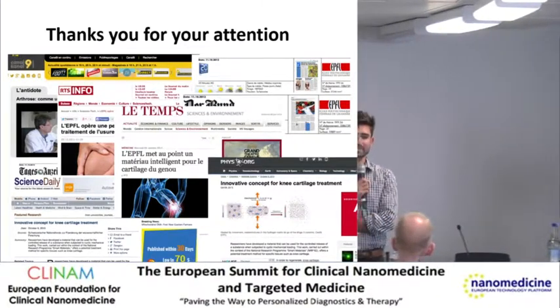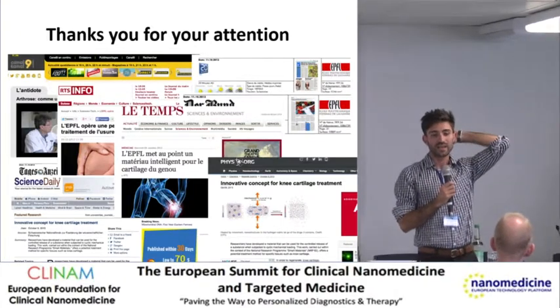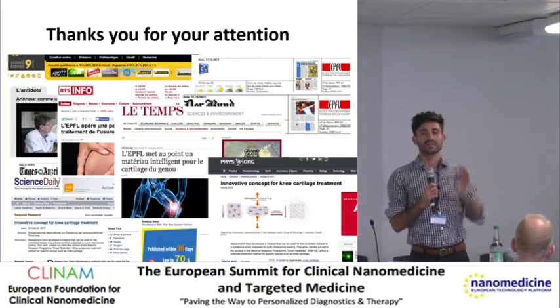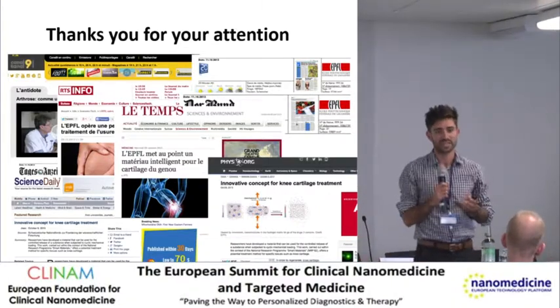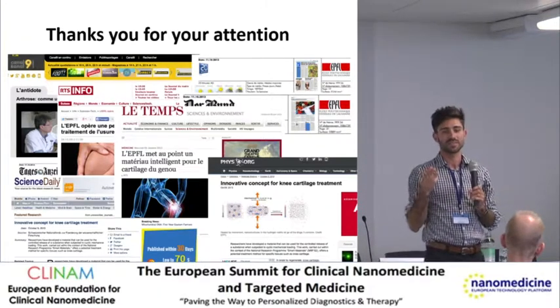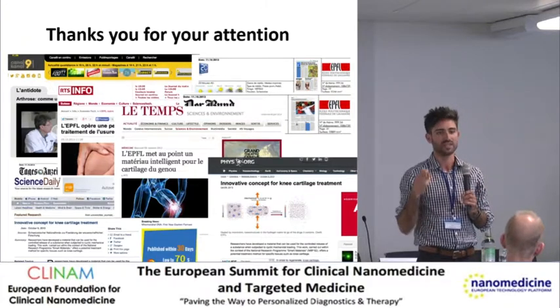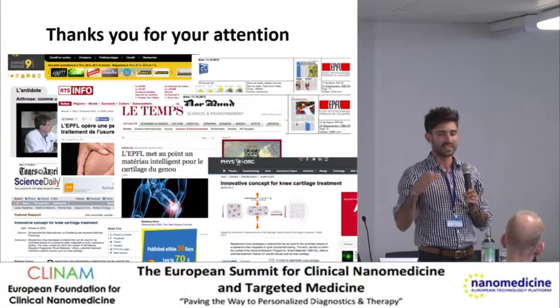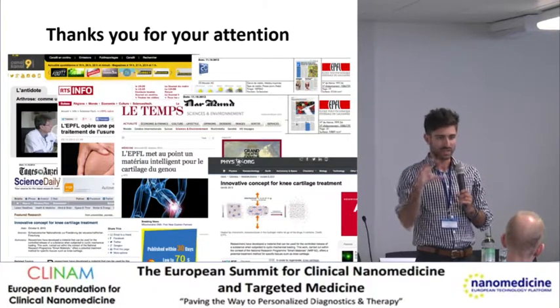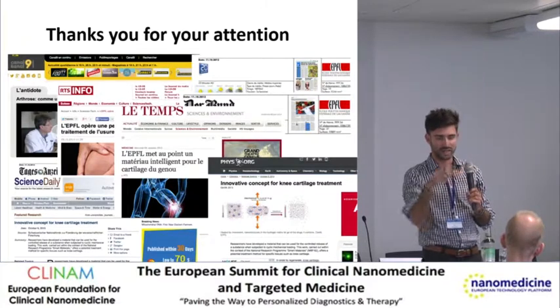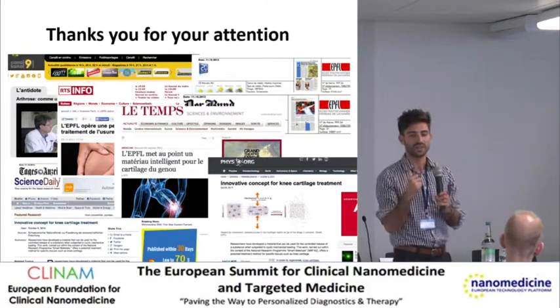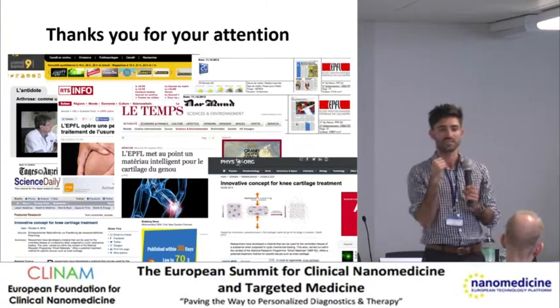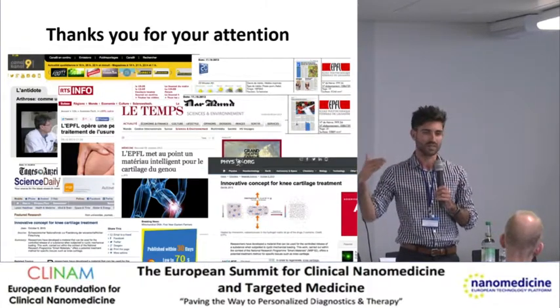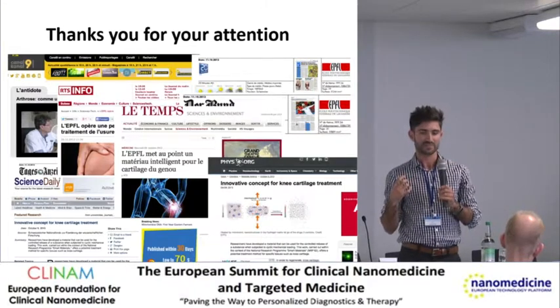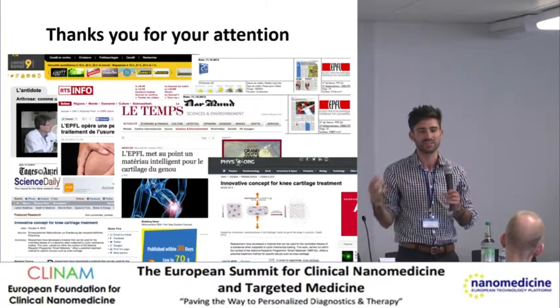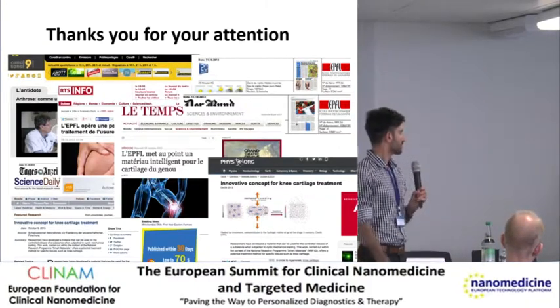Can you say how your test drug is bound in your hydrogels and what mass ratio you can load it up to? So as I told, the idea was that you have no interaction with the drug. What really keeps the drug is the permeability of the gel. For example, these gels have a mesh size of less than 2 nanometers, which is from experimental measurement of the release. So they are basically not bound to the gel. They are free inside the hydrogel, but you don't have high passive release, as I showed, because of the special properties of the gel: it has a degree of hydrophobicity, so it is not very inclined to release the drug when there is no force acting on it.